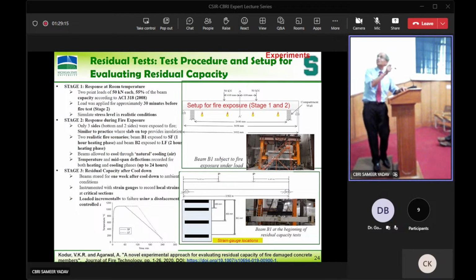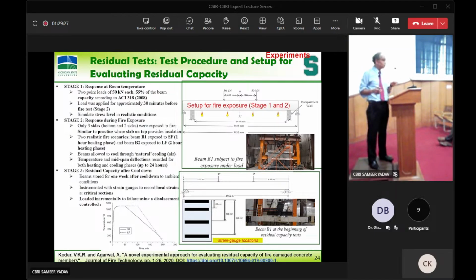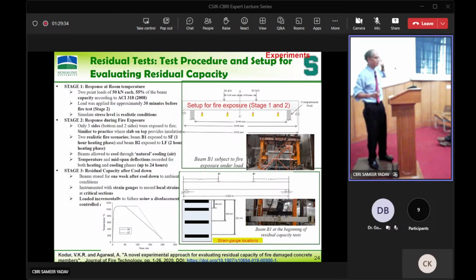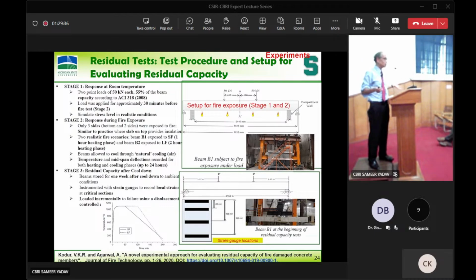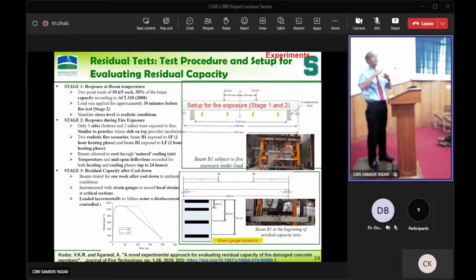Doing a residual capacity test is different from a fire resistance test. You cannot do it in one shot. You have to do 3 stages of analysis or experiment. Just before the fire started, you need to know how much capacity the structure has. This building was built in 1947. Today, we don't know what the capacity of the beam really is. Even at that time, if you look back at drawings, you cannot take them at face value, because based on this you have to establish the real reserve capacity.